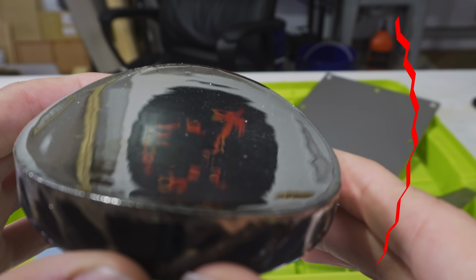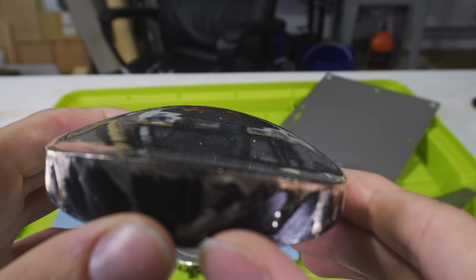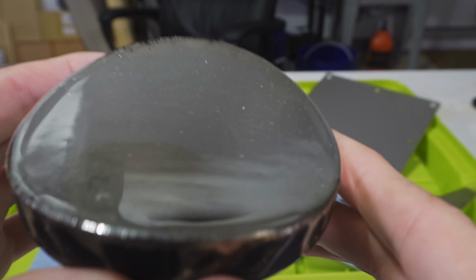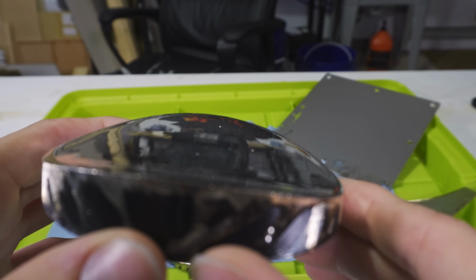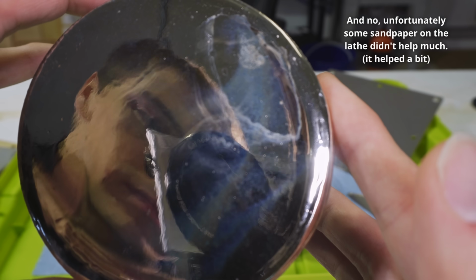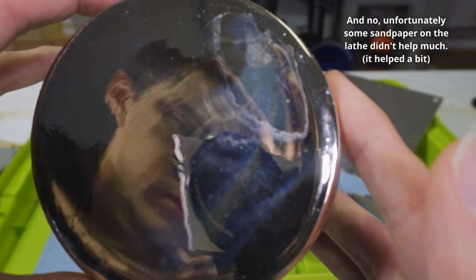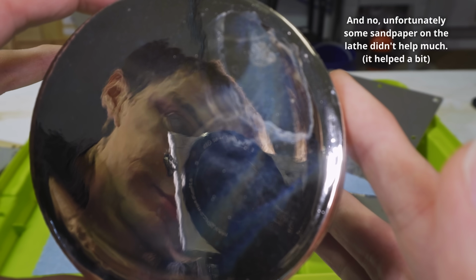A closer inspection shows that the striations I was seeing followed the layer lines of the print, and every handful of layers, the surface quality changed. So when this was coated with silver, there'd be a few millimeters in a row, then another few millimeters pointing in an ever so slightly different direction, and then a few millimeters pointing in ever so slightly another direction, and so on. While the large-scale shape may have been a perfect parabola, and the nanoscale shape was mirror smooth, the mid-scale shape was giving me problems.